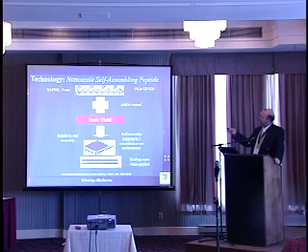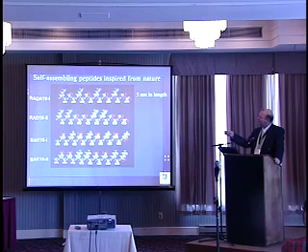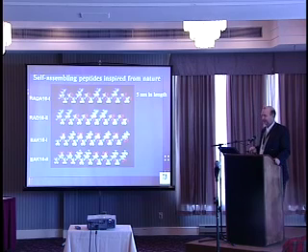So this is an arginine, alanine, aspartate, alanine. It's 16 amino acids put together in the same way. It's a RADA repeat times 4. You put it with any ionic solution, it will actually form beta sheet. And I was really concerned about this when we first put it into an animal because I was thinking self-assembly of a small protein-like structure, prions. That was the first thought I had. So, and I'll come back to that.